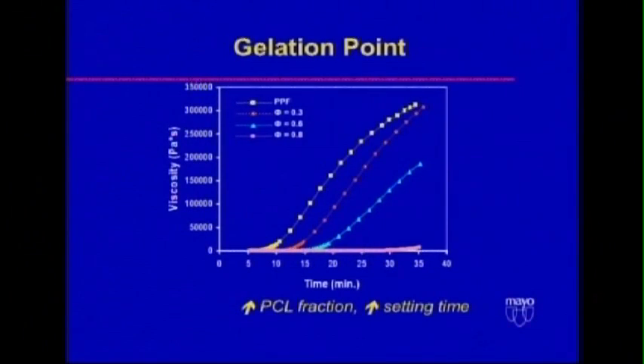And so with the PCL fraction increasing, we can change the gelation point. Now, why is that important? I mentioned, let's start with a clinical need. The polymer that orthopedists are most used to working with is polymethyl methacrylate. We're creatures of habit. You get something with a powder in it, you get something in a brown vial with fluid in it, you break the vial, you mix the two, you put them together.